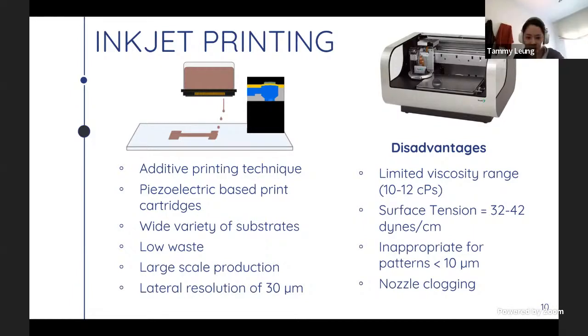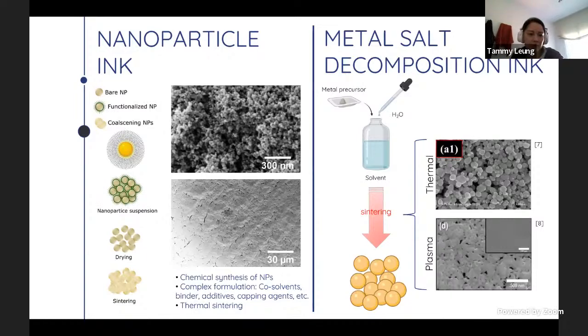However, most of the disadvantages include the fact that there are many restrictions on the inks that have the ability to be printed here. Meaning, for example, nanoparticle inks cannot have particles larger than 300 nanometers, as it is likely to clog the print head. So for this reason, the inks themselves must be adapted to inkjet printing in order to print consistently. And still today, nanoparticle inks remain the most dominant and commercially available ink specifically for inkjet printing.